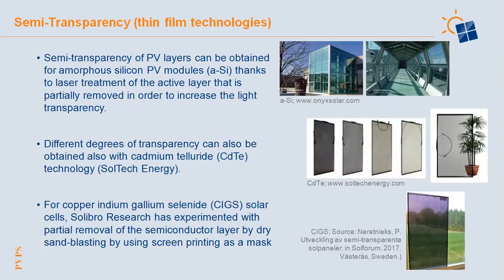With thin film technologies, you can also reach a certain degree of transparency. Here I give you three examples for different thin film technologies. In the first example, the amorphous silicon layer is partially removed by a laser treatment, and then you get this nice transparency. So you can have it in windows and facades, and it gives you a shading effect, but you have an active facade which is producing electricity as well. The second example with cadmium telluride, and the third with CIGS, have the same effect. You have a high degree of transparency, but you lose, of course, a certain amount of electricity production.